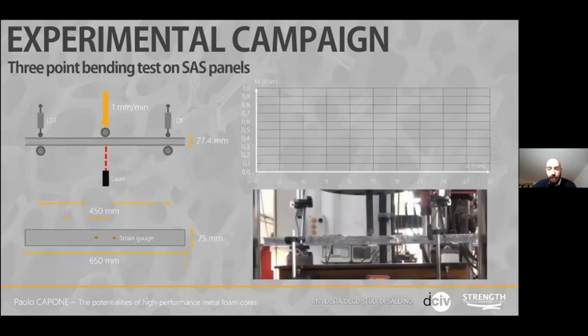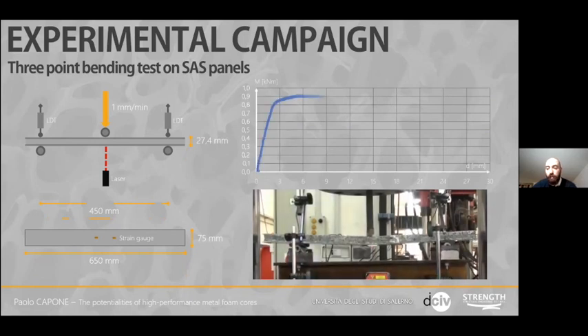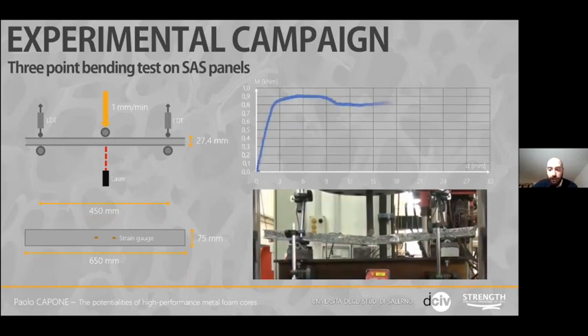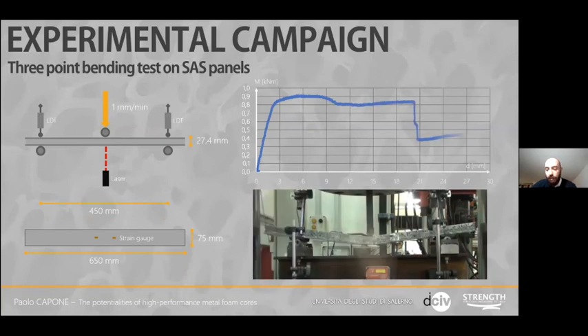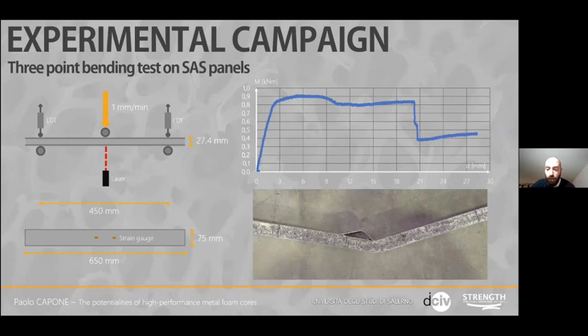In the third and last step, the performance of SAS sandwich panels in bending has been assessed. The assembled panel has reached a bending moment of about 1 kN, which, considering that the tested specimen has a width of 75 millimeters, referring to an equivalent panel of 1 meter width, the corresponding bending strength would be about 14 kN. After a displacement of about 20 millimeters, the specimen lost almost completely its resistance due to the buckling of the compressed top skin.